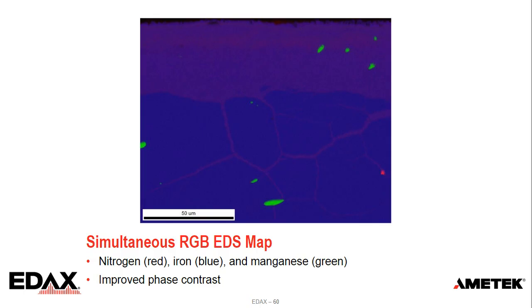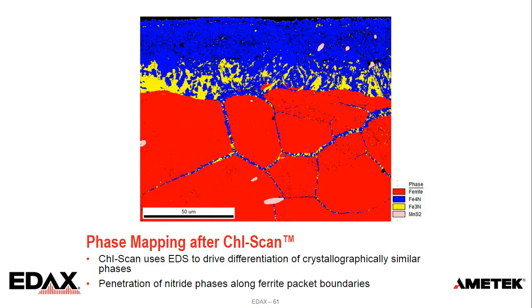So this is just that same RGB EDS map where we can see the nitrogen in red, and you can kind of see, it's a little hard to see, but you can see the shading of where the nitrogen is present. We can see where the, I put manganese, I don't know if it's the manganese for the manganese sulfide. And then we can use that to select the correct phase for each point based on the chemistry. From that, we can differentiate better the crystallographically similar phases. We can see the true phase distribution, and then we can also start to see how the nitride phases are present on the outer layer, as well as how they're penetrating into the microstructure through the ferritic packet boundaries.